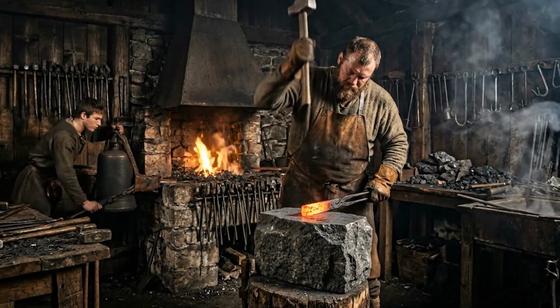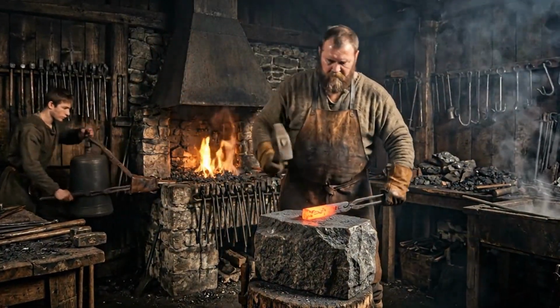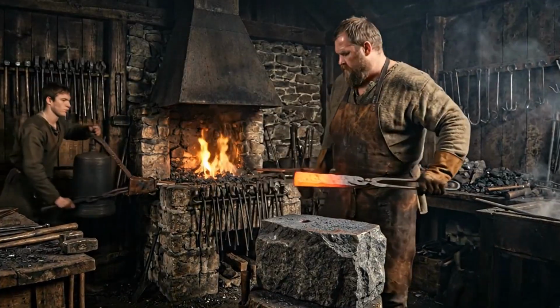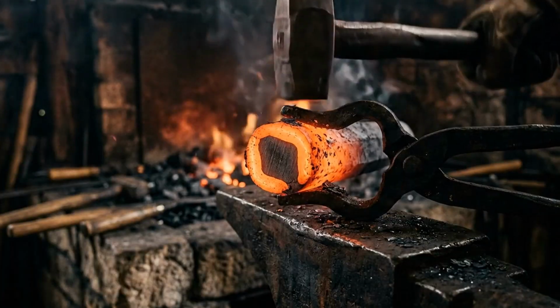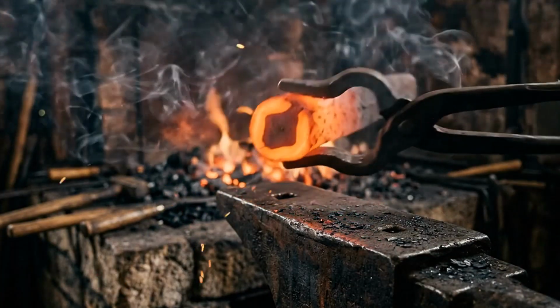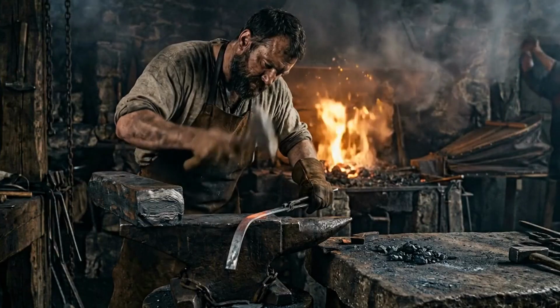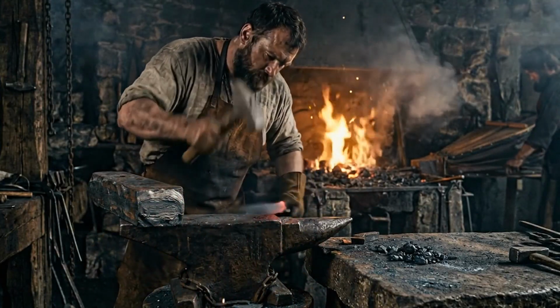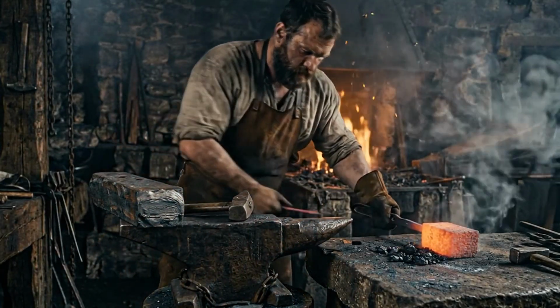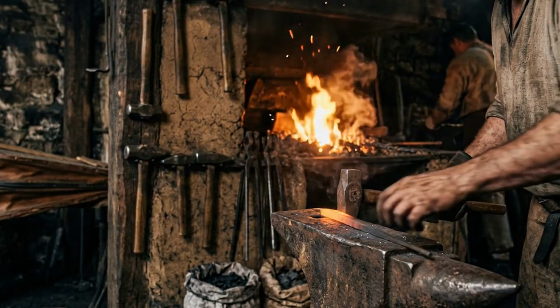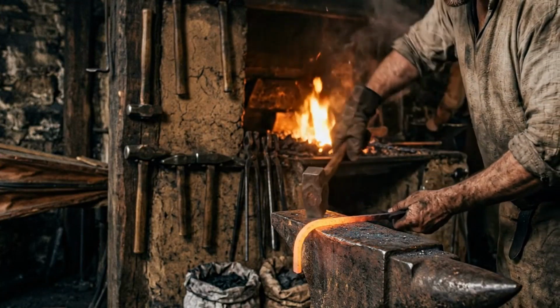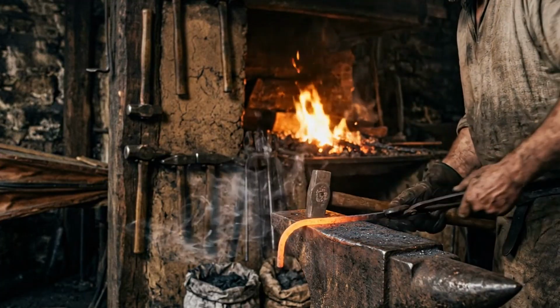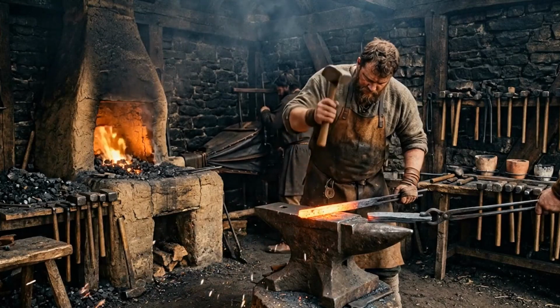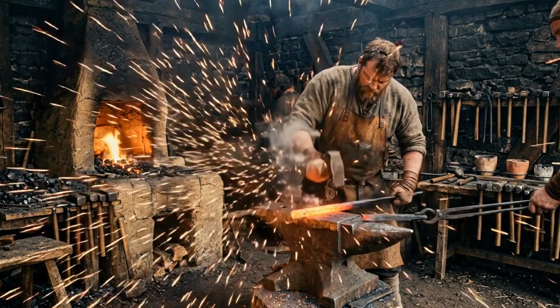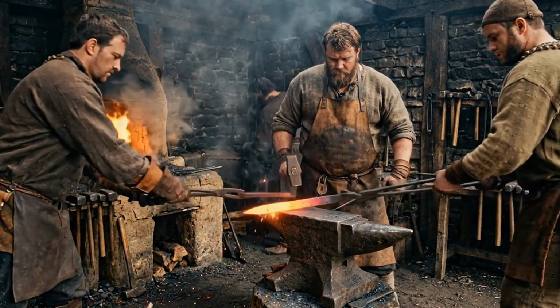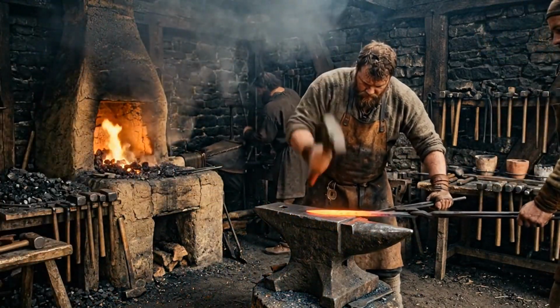The result was a composite billet with a hard outer shell encasing a tough inner core, a structure that addressed the fundamental contradiction at the heart of blade design. A blade that is hard enough to hold an edge is brittle enough to shatter under impact. A blade that is tough enough to absorb shock without fracturing is too soft to hold an edge. The laminated construction of the katana resolved this contradiction by assigning each function to a different material within the same